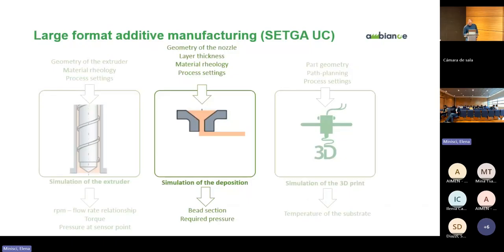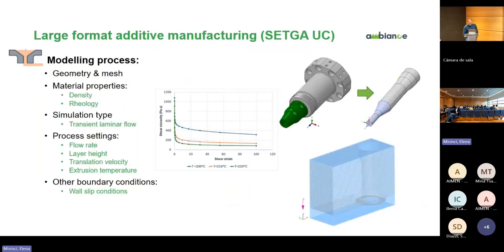Next one is the nozzle model. Nozzle model, I have mentioned, we use again a CFD simulation software. We use the same characterization of the rheology of the polymer melt as before, but we are focusing on what happens on the very last part of the extruder. That is this green part, that is the nozzle, and the layer thickness on the substrate. That is also a restriction for the flow that needs to be taken into account for the pressure loss prediction.